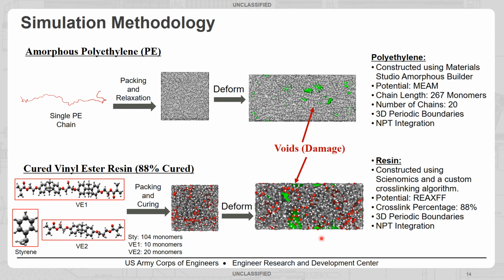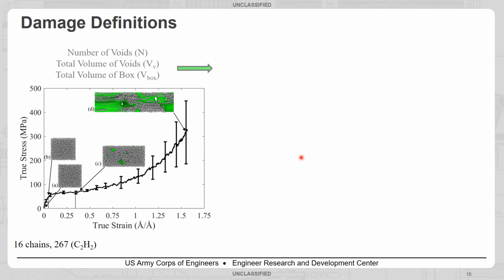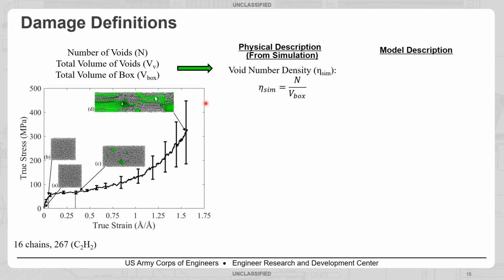Here they're deformed at a constant strain rate. So we compare them at the same strain rate and the same temperature, and look at how voids or damage evolve during deformation. To do that, we have to define damage. Here we can count the number of voids in our system during deformation. We can count the total volume of voids, and we know the total volume of the box. That allows us to define some damage terms. First, the void number density, which is equal to the number of voids in the system divided by the volume of the box, so you have voids per unit volume. Average void size is the total void volume divided by the number of voids. And finally, void volume fraction, which is the ratio of void volume to solid volume, which is the most important term here for quantifying damage.